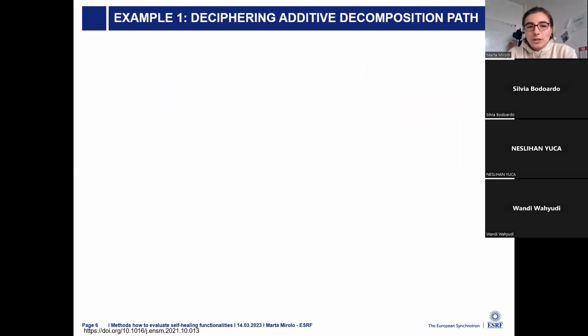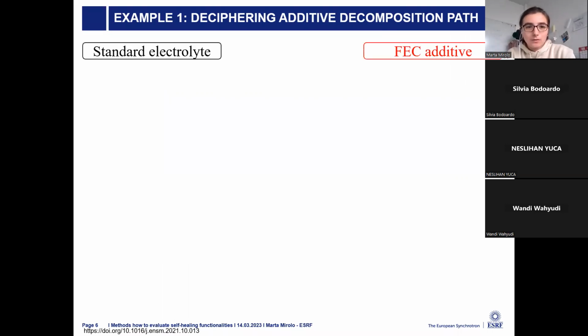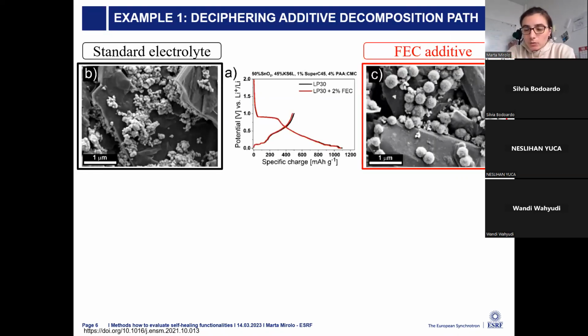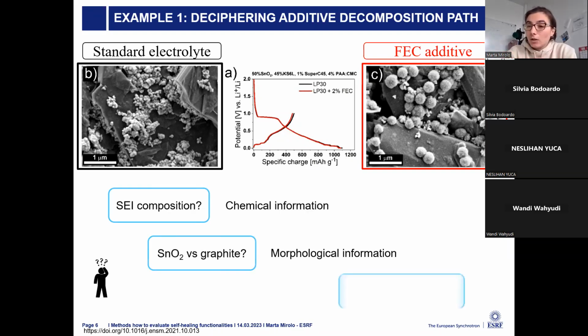The example that I will show here is how to investigate, for example, the additive decomposition path. So we had an electrode which is composed of graphite and tin oxide, so it's a composite anode material, which was cycled with a standard electrolyte and with the same electrolyte, but with the addition of FEC additive. And with the FEC additive, there's an improvement in the electrochemical performance of the graphite tin oxide electrode. So the question is, okay, why is there this improvement? Is it the SEI composition that is different from when we use the FEC additive compared to the standard electrolyte?